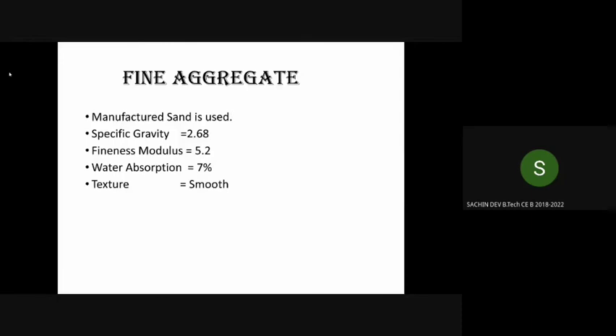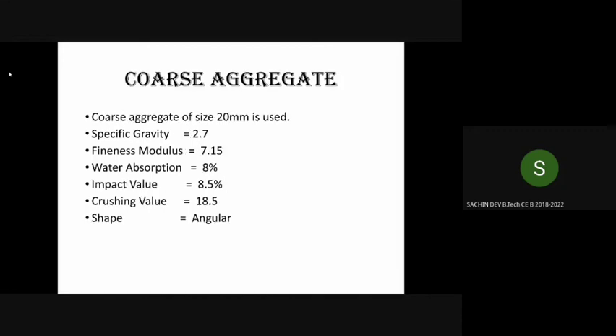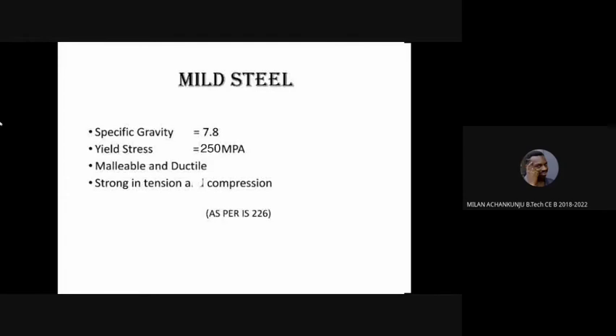Next one is fine aggregate. We use manufactured sand as a fine aggregate. M sand has a specific gravity of 2.68, and the fineness modulus is 5.2. It has a water absorption of 7%, and it provides a smooth texture. The coarse aggregate we used is the 20 mm size, and the 20 mm size coarse aggregate has a specific gravity of 2.7, and it has a fineness modulus of 7.15. Water absorption of the coarse aggregate is 8%, and it has an impact value of 8.5% and crushing value of 18.5. And we use angular shaped coarse aggregate for our construction purpose.